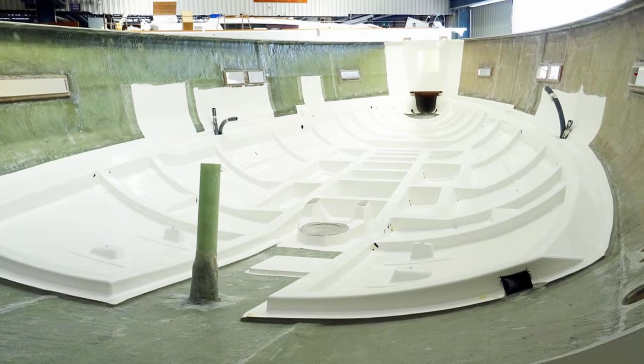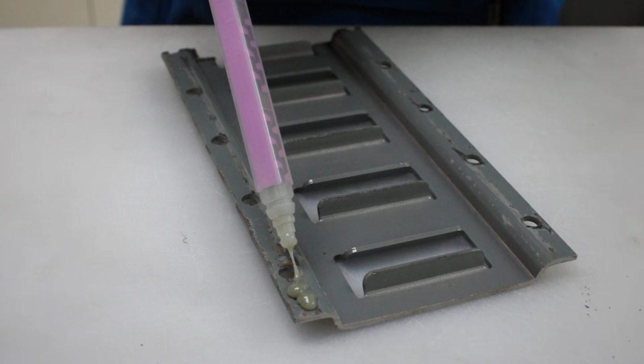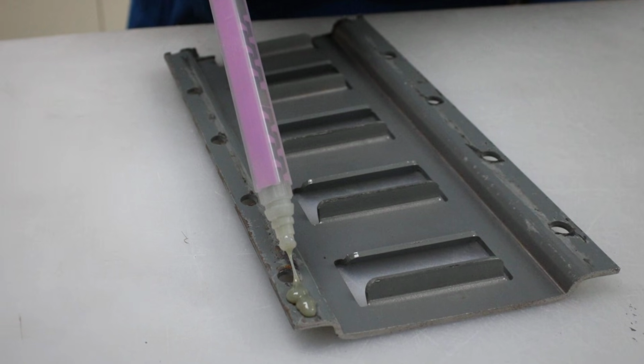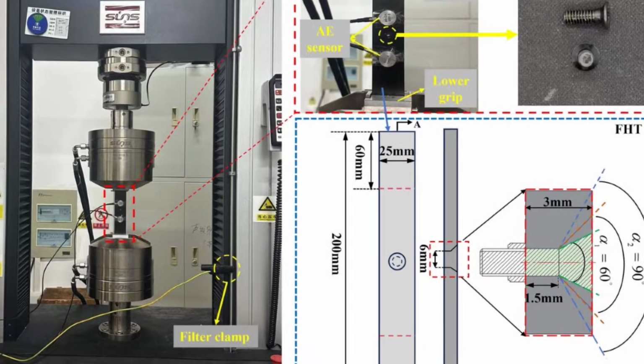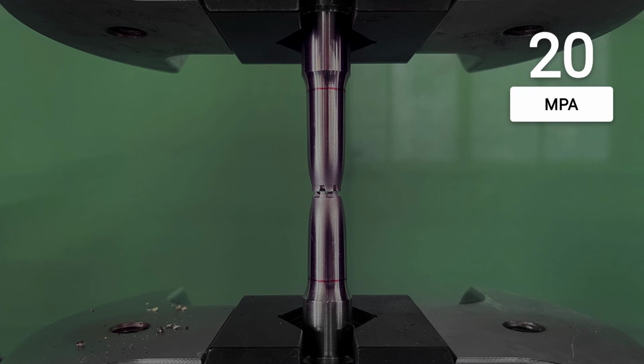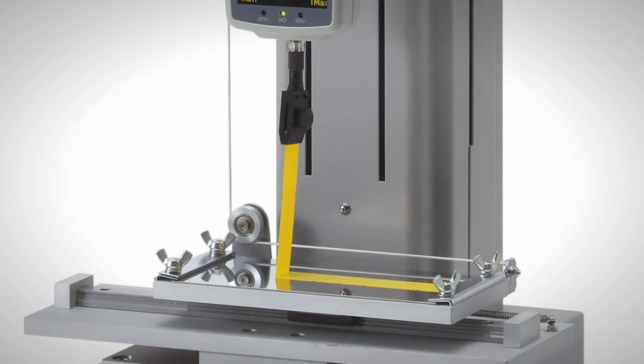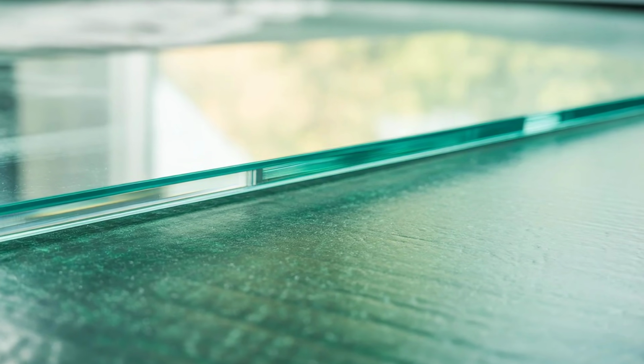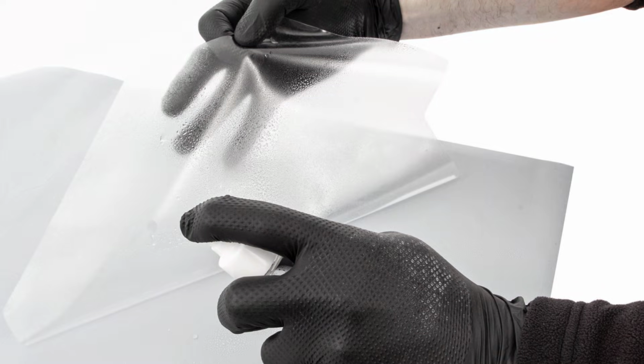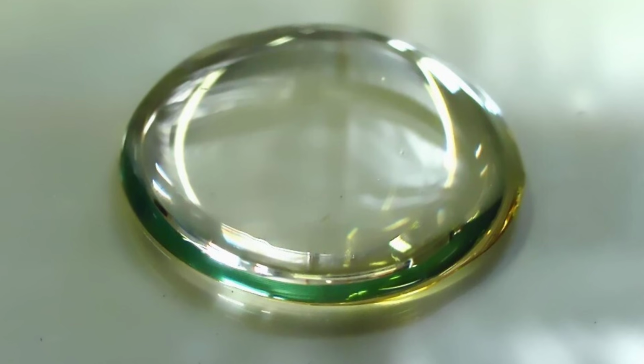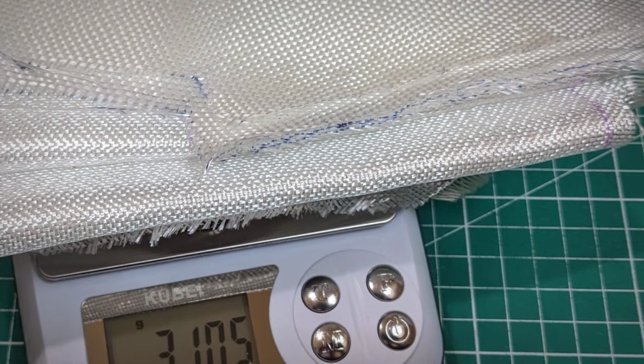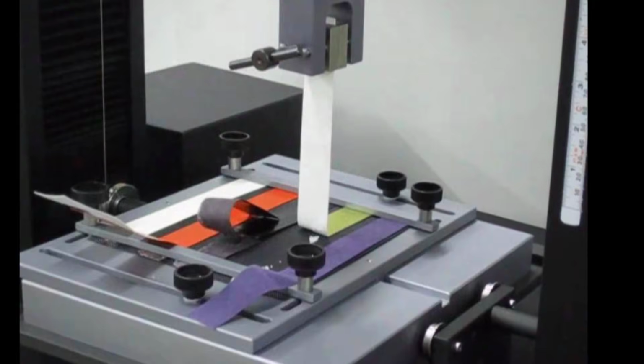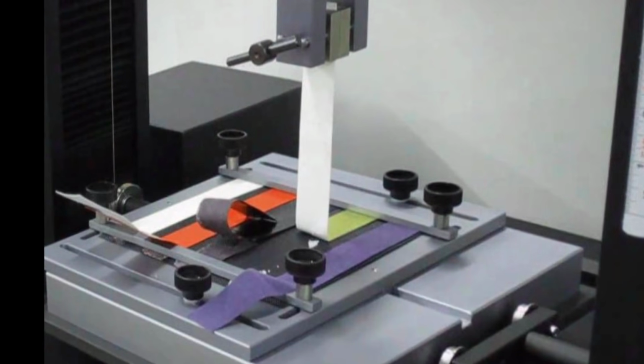The grid systems in today's production yachts use high-modulus methacrylate adhesives, for example Plexus, whose tensile strength on paper exceeds that of the fiberglass itself. In a lab, you can pull a dog bone coupon to 20 megapascals and watch the glass fail before the glue does. But that is only half the story. The real weakness lies where the adhesive meets the hull's cured polyester skin, the so-called secondary bond. This is not a chemical marriage. It is a handshake across a cold, inert surface. The glue cannot truly bite into the cured resin, so it relies on surface energy, roughness, and hope.